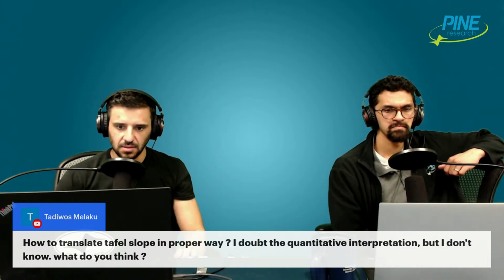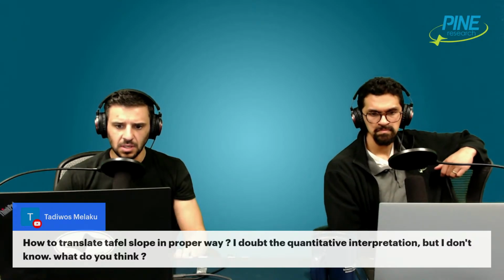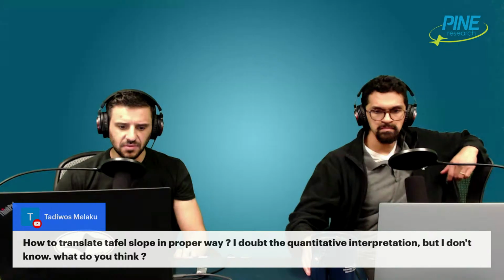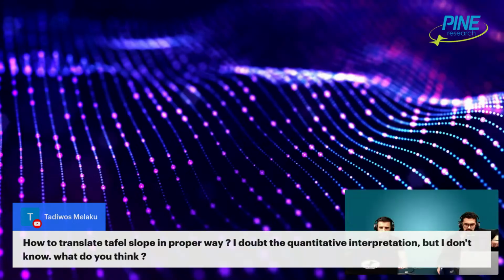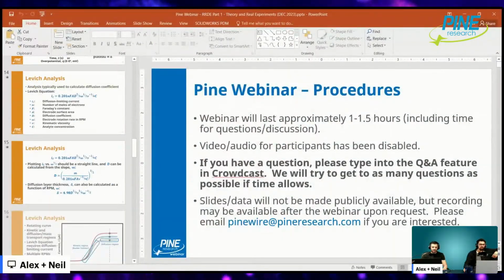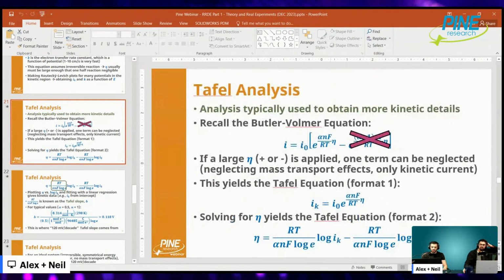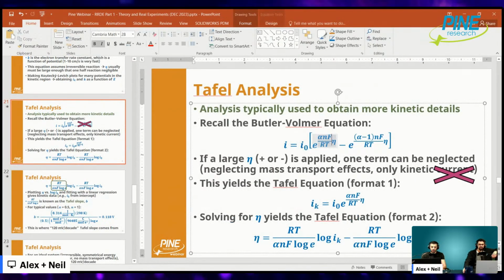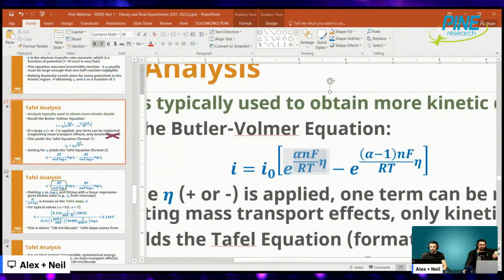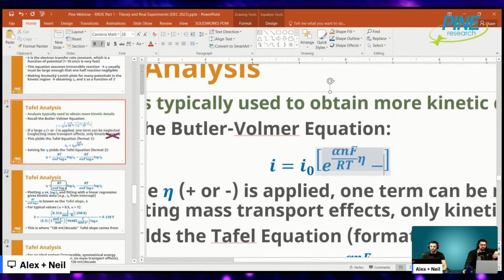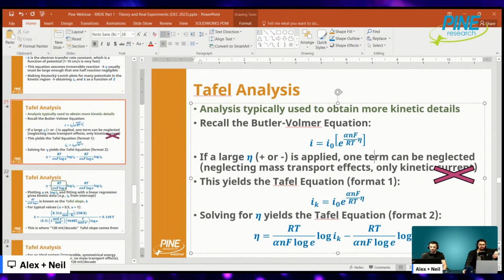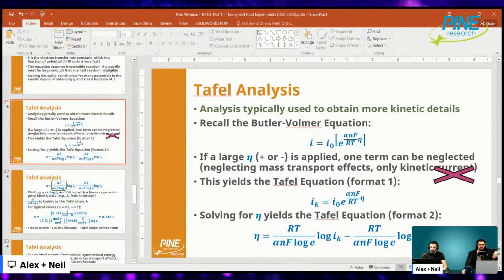Let me find that slide for you, and I'll show you where the Tafel slope comes from, the Tafel equation. I have that here. So the Tafel equation comes from the Butler-Volmer equation, which is this equation right here. Okay, this is the Butler-Volmer equation. What we do is we get rid of one of these terms, so goodbye. Okay, this right here is the Tafel equation. It's half of the Butler-Volmer equation. And what we do is we solve for the overpotential. So we solve for eta here.